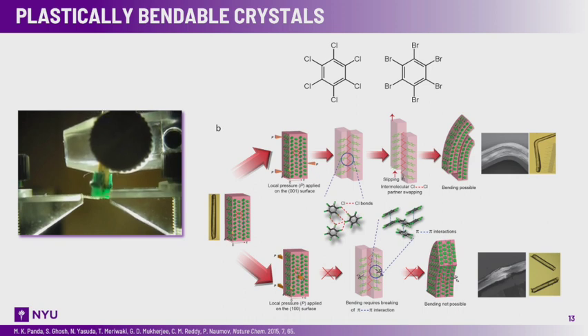So we did a lot of research on plastically bendable crystals, and one example is shown here. Basically, this anisotropy comes to full extent, I would say, when you look at the mechanical properties. In this particular case, if you affect the crystal on one side, you get sliding of these layers, and the crystal will bend plastically. But if you push it on the other side, because you want to break the pi interactions, then of course it will break. And so you have a incongruous response of the same material when you affect it on different faces.